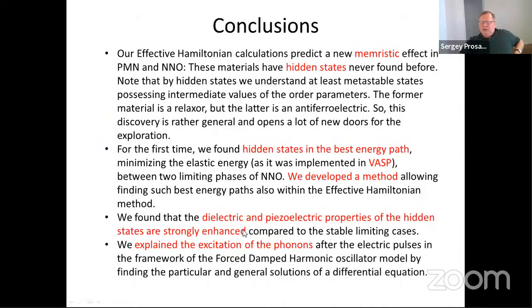So let me just show the conclusions that we found. The two materials which we considered have memristive effect, have hidden states, and these hidden states are seen from the calculations of the response to the train of electric pulses, and in the energy path between different phases. We also found that dielectric and piezoelectric properties are enhanced in these hidden states, and we also qualitatively explained the excitation of the phonons within just a harmonic oscillator model.